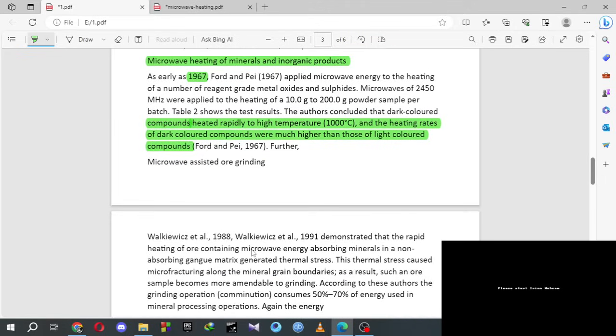Further, microwave assisted grinding. Researchers demonstrated that rapid heating of ore containing a microwave energy absorbing mineral in a non-absorbing matrix generated thermal stress. This thermal stress caused microfractures along the mineral grain boundaries. As a result, such an ore sample becomes more amenable to grinding. According to these authors, the grinding operation consumes 50 to 70% of the energy used in mineral processing operations.